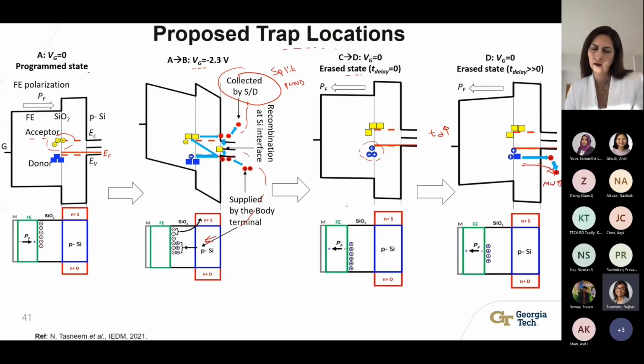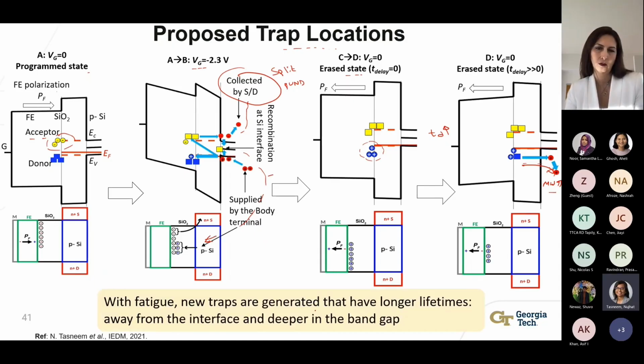Now, our experiment showed that as we keep on cycling the device, the amount of emitted electrons and emitted holes becomes less and less. Which indicates that with fatigue, new traps are being generated that have longer lifetimes, which means they are away from the interface and deeper in the band gap. So this work was presented in IEDM in 2021. Now this is just a qualitative model.